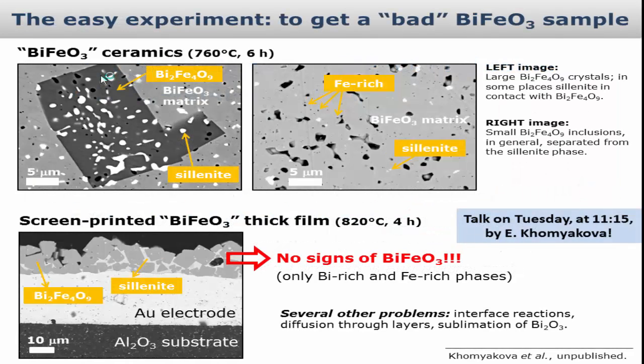So I'll start with processing. Those of you who work with BiFeO3, I think you're familiar with this sort of microstructure. These are the secondary phases that are usually present when you sinter BiFeO3. This dark region is the iron-rich phase, and these bright regions are the sillenite, the bismuth-rich phase. These are the two phases that also appear in the phase diagram.